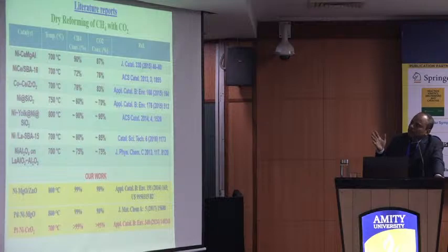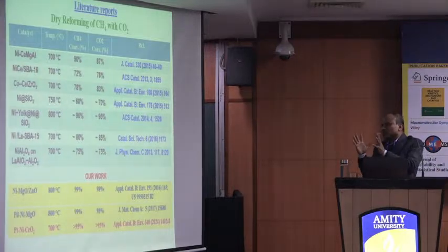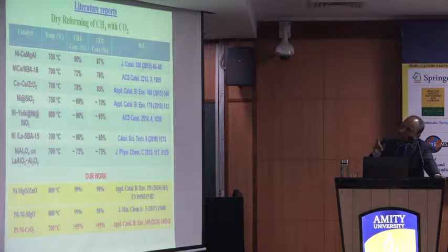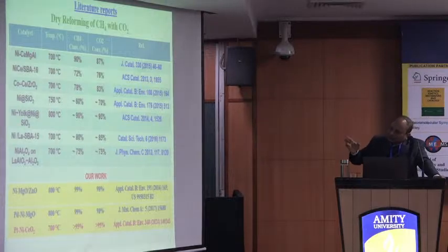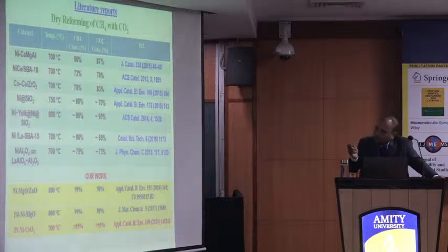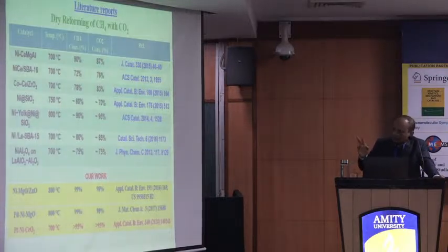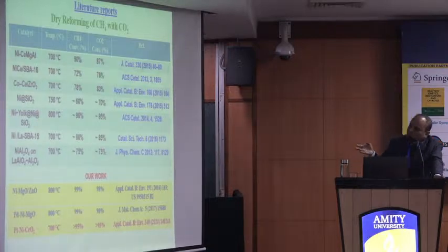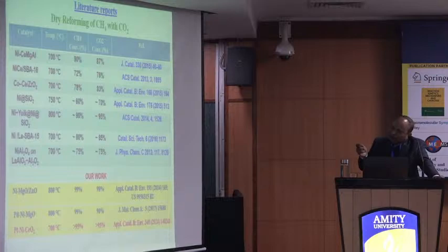Then I come to dry reforming of methane. There are also several reports in the literature for dry reforming of methane, but the main problem here is also stability. We are working in this area too, and we have developed several catalysts and patented them. Initially, we tried nickel supported on magnesia-zinc oxide. It is stable up to almost 100 hours. Then we added a small amount of palladium, 1.2%, and it showed almost 200 hours of stability. And recently, we developed a catalyst with a very small amount of platinum, 0.5%, supported on ceria, which is stable up to 700 hours.